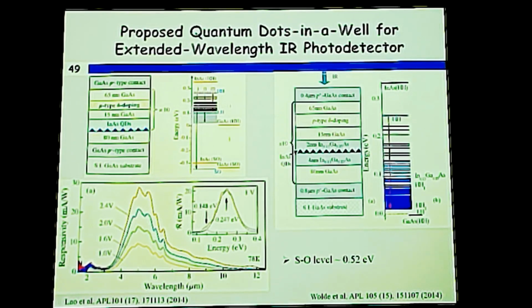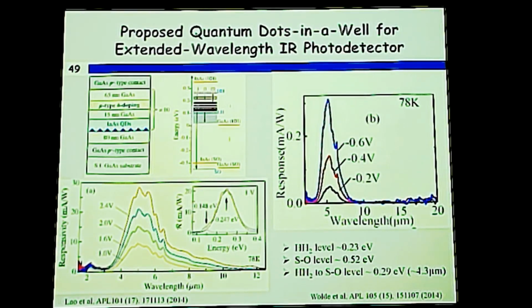Again, this is also 78 K. Mostly we do the measurements at liquid nitrogen, and if the device is operating, we try to get a higher operating temperature. For this one, 3 micrometer, that is not clear here, but maybe somewhere around there. This one didn't show. Probably only this peak was picked up to show for this one. So 3 micron in this one is not there, but probably around 2.2, probably that was there, I guess.